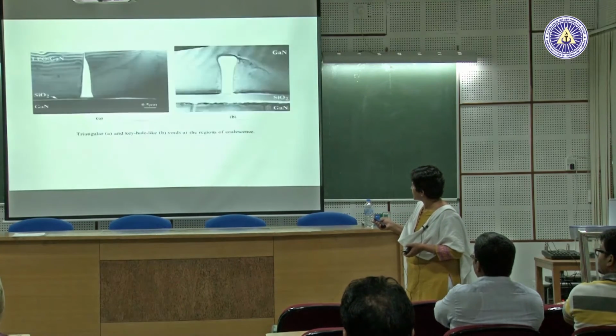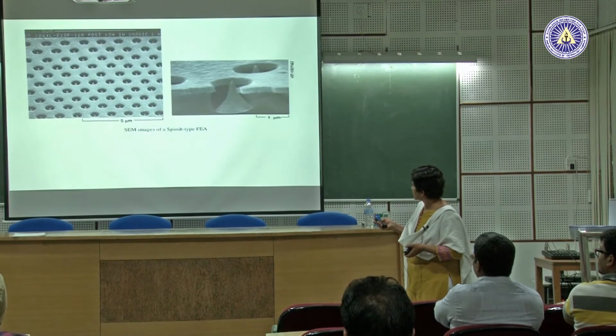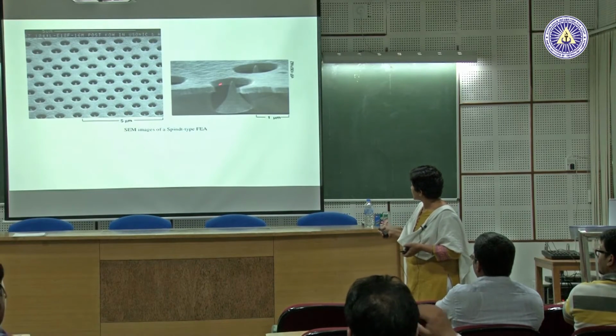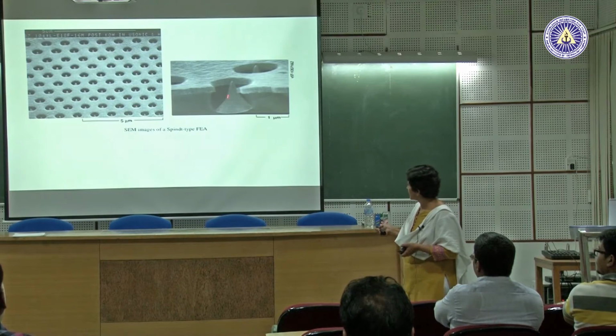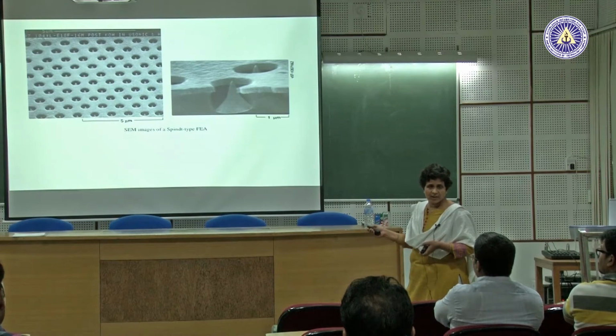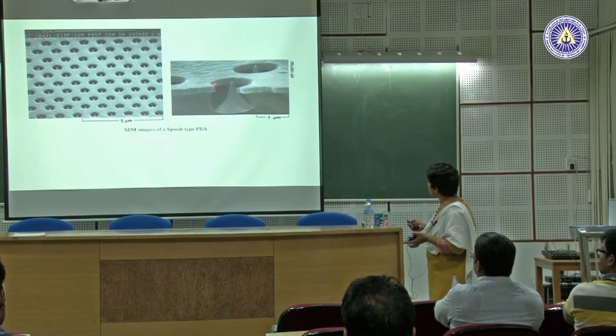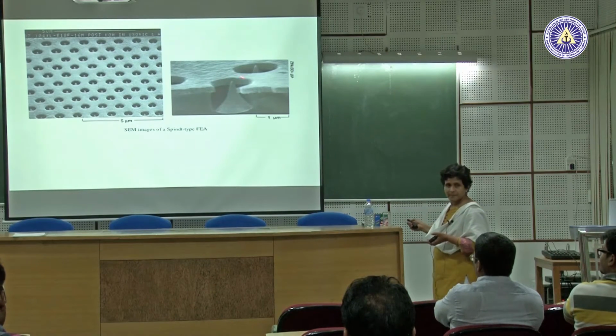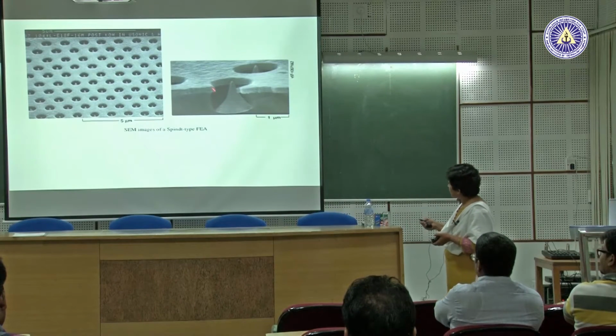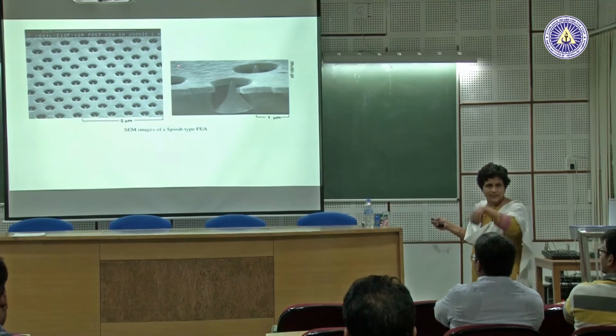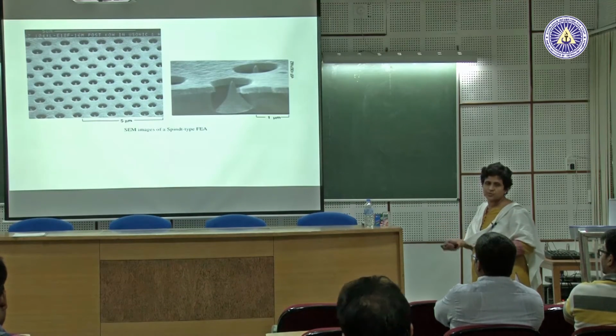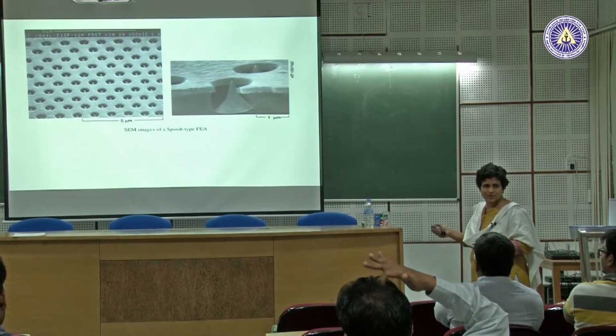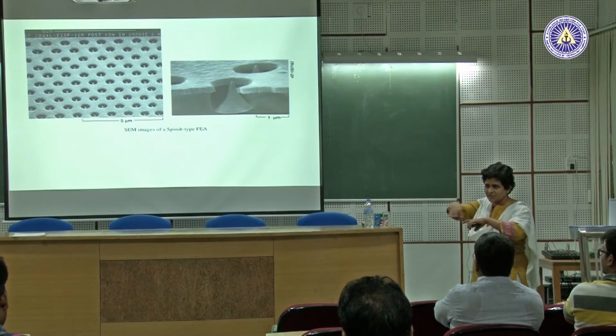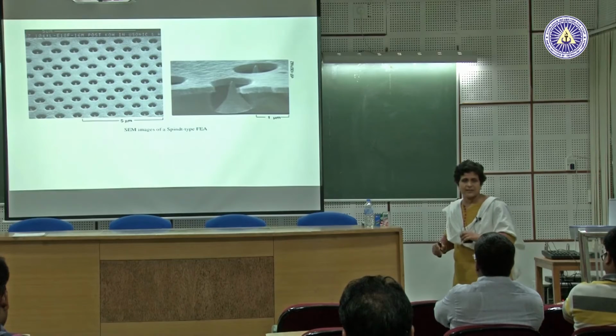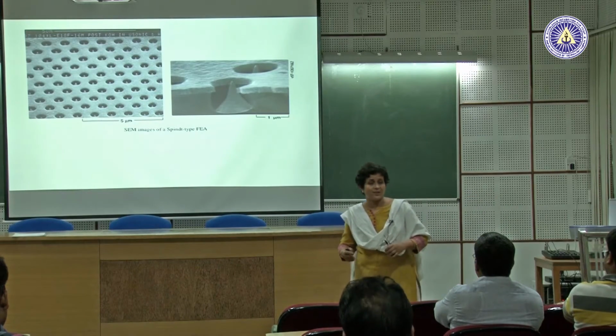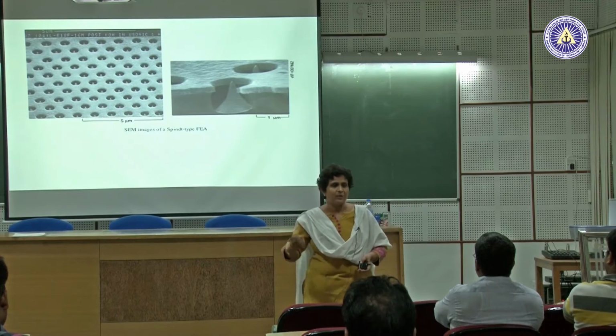I will skip all this, show you one more. This is all evaporation. This particular cone is being created by a deposition technique. The way it is created is, first you do the lithography to create this hole, right, and then when you deposit it, because of the way the shadowing of the incoming atoms works, it deposits in the form of nice cones. The film gets deposited in nice cones because of the geometrical constraints given. It was used for making field emission arrays of molybdenum for some display applications.